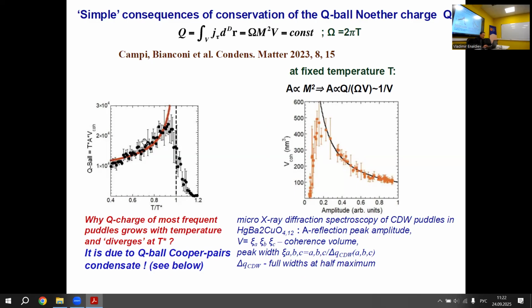So these are experimental points, and here, for example, these experimental points show that starting from some finite amplitude, the volume of the puddle decreases along this curve. The curve is theory, which I'm telling about. So curves are theoretical results and points are experimental results. So indeed, they found that the increase of scattering amplitude causes decrease of the volume of the puddle.